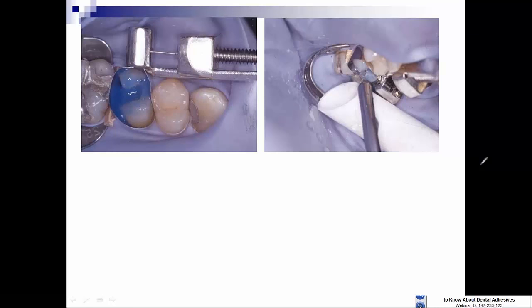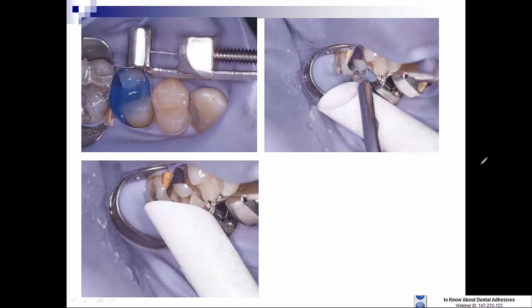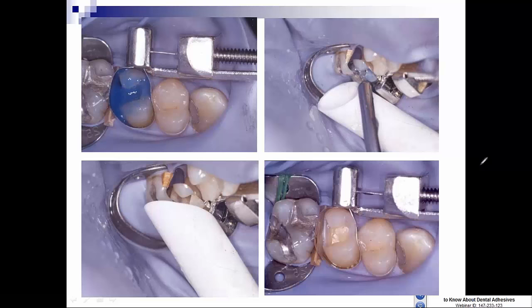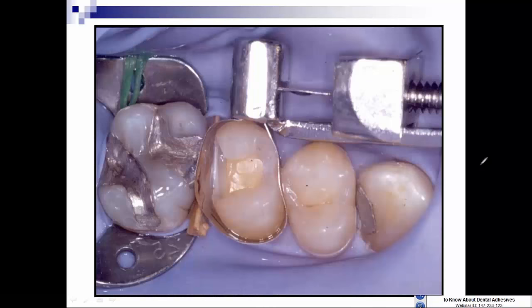So we have high volume evacuation there, removing the acid. Remove the air water syringe, and for a count of 1001, 1002, aspirate the excess moisture off of the tooth, leaving the tooth typically visibly moist in this picture. So moist dentin is the absence of visible and forceful air directed onto the dentin to prevent this collagen collapse. And so this would represent a reasonably moist dentin, absence of drying. Now, if in the corners of a prep there's some pooled saliva or crevicular fluid seepage around the matrix band, simply roll up a cotton pellet and dab that excess meniscus of moisture away.